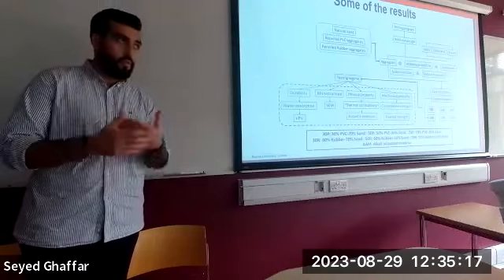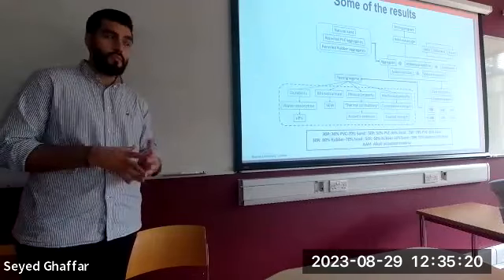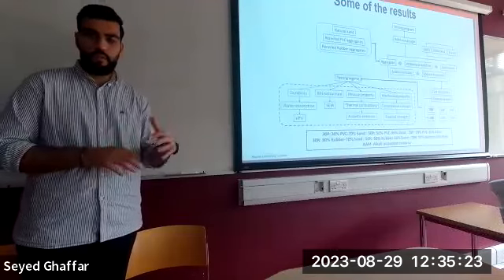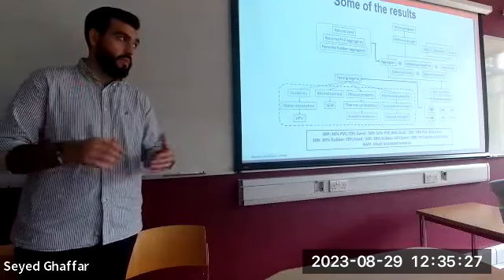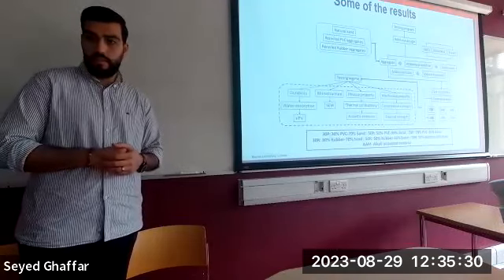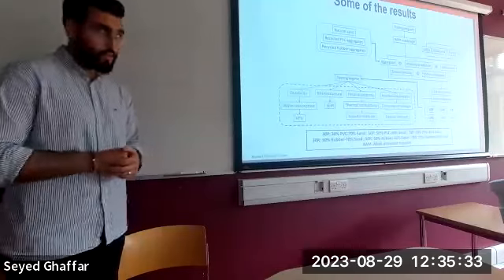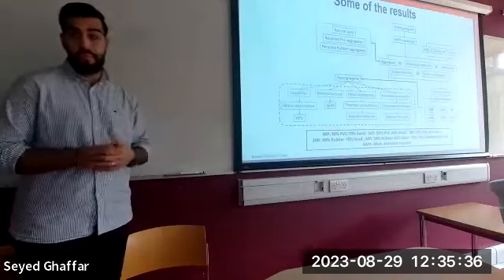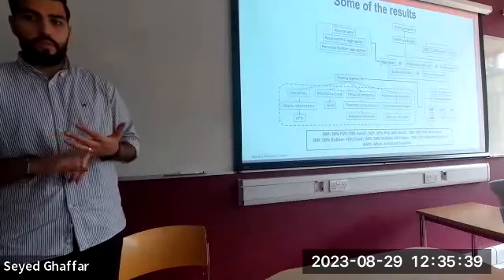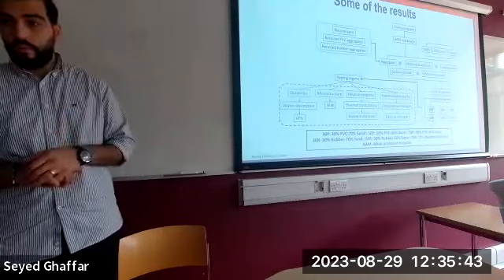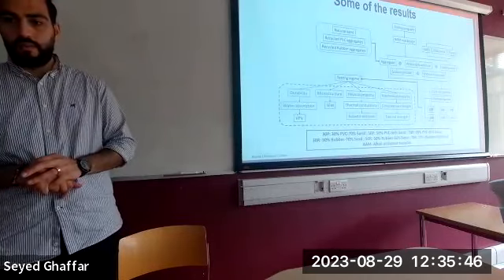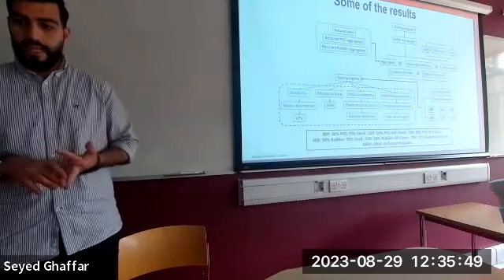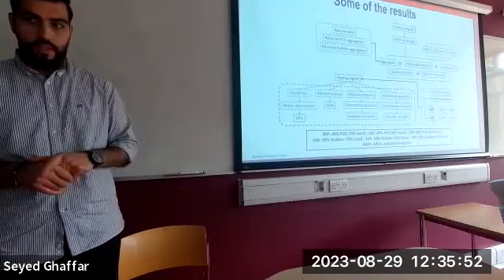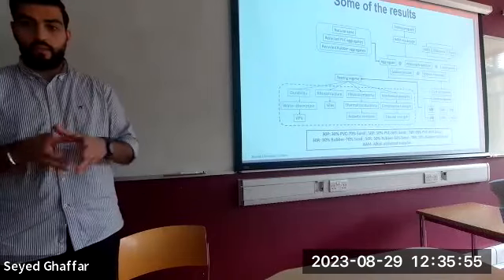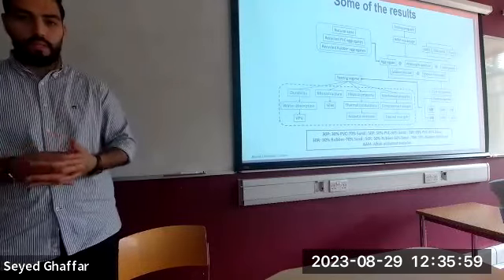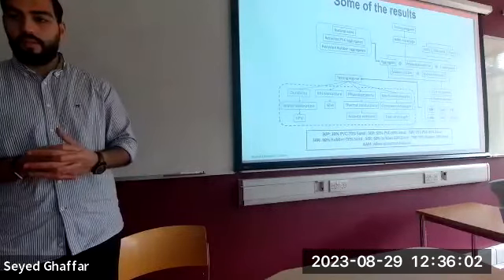We use some additives to improve the rheology, the workability, and the strength of our materials. These are very small percentages of additives, such as nanoclay. For the aggregates, we use natural sand as our control sample benchmark. We use recycled PVC aggregates, polyvinyl chloride, and also rubber aggregates to replace sand. Our replacement ratios were 30%, 50%, and 70%. We tested the concrete blocks developed from these recycled aggregates for a variety of parameters and properties, such as durability, microstructure, physical properties, and mechanical properties.